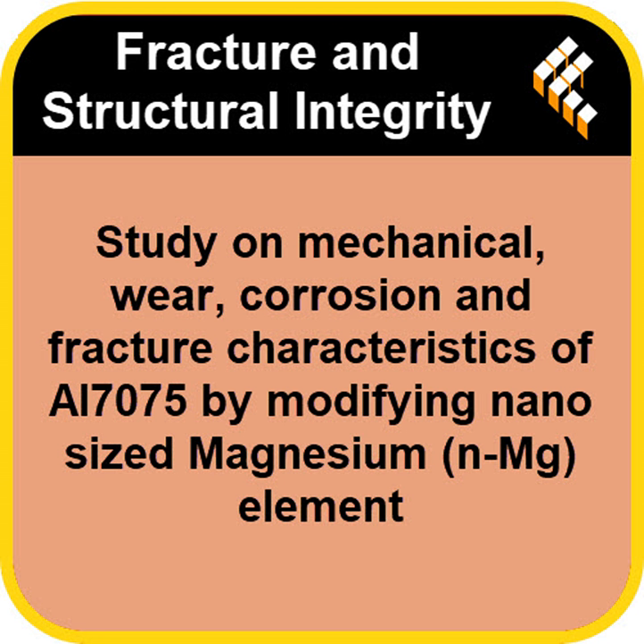And here's where it gets really interesting. Uh-oh. They push past that optimum. When they went to the highest concentration, 2.5 weight%, the results actually got worse. They dropped. Both hardness and tensile strength dropped compared to the 2% sample. Why would that happen? If more magnesium means more of that strengthening compound, why would the strength suddenly decline?